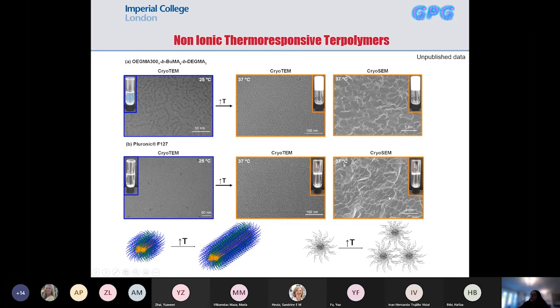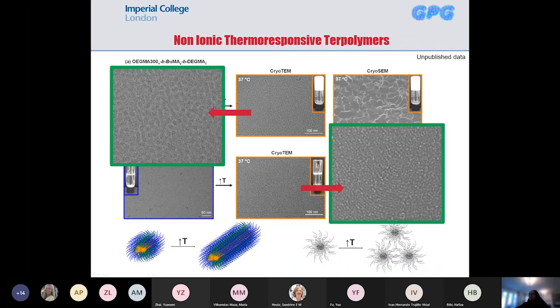With SEM, what you observe is obviously at a much bigger scale, so you don't really see a big difference between the two. But for the cryo-TEM of the pluronic, you do see that the structures are much smaller, and in some cases here you see the lamellar arranging of the spheres. So I've tried to zoom in to see it a bit better here. You have lamellas forming from the spheres. Well, in ours, you have some worm-like micelle structures. But obviously the structure of the gel is quite dense and it's not that easy to see.